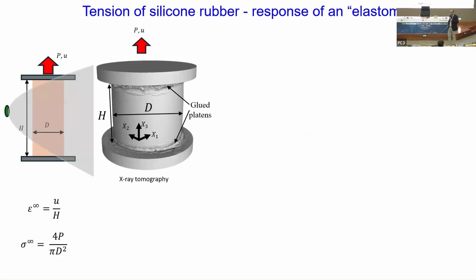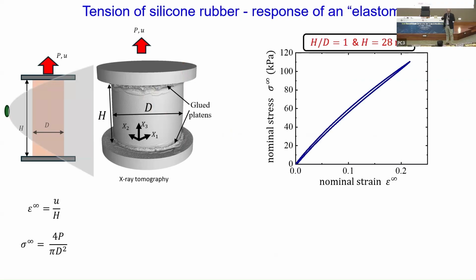Okay, so let's go to the measurements. So, very simple measurements. We take a cylinder of this material. We glue it to platens, as you can see here. And then we pull it in tension. And then you define sort of a stress-strain curve.